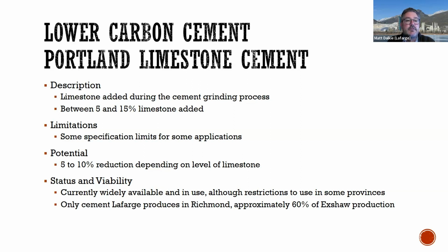But the potential is a 5 to 10% reduction of CO2 depending on the level of limestone. And that change is something that can be done for most ready-mix producers and for most applications without any change at all. So it is currently widely available in Canada. As far as our production, Lafarge production, this is the only cement that we produce in Richmond, and it currently accounts for around 60% of the cement production at our actual facility.